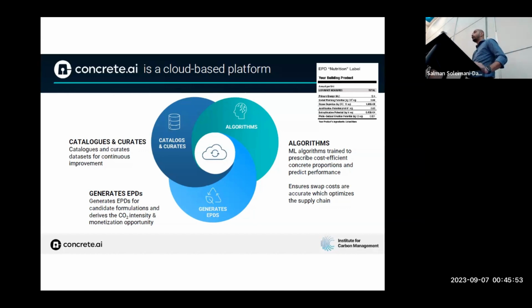And when I talk about 30 to 40% over-design, I'm not talking about what is specified by the structural engineer. You've got the structural engineer that puts in a safety margin, you have a concrete producer that puts in a safety margin. You basically add the two up. That's the extent of over-design that you actually get. Listen, all this comes down to is the sophistication of the operation. You've got a really sophisticated ready-mix producer, they've got tight distributions. These are about the best concrete you can get. Even there, you'll end up with 20% over-design pretty comfortably. You go to a poorly run operation, you'll see 50, 60% routinely.